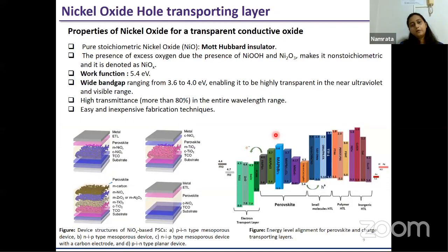Here are a few more properties of nickel oxide, and why it is a suitable transparent conductive oxide. At first, pure stoichiometric nickel oxide is actually a Mott-Hubbard insulator, so technically it should not be used as a p-type semiconductor to transfer charges to the electrode. But the presence of excess oxygen, due to species like nickel oxide, hydroxide, and Ni2O3, makes it a non-stoichiometric material, denoted as NiOx.